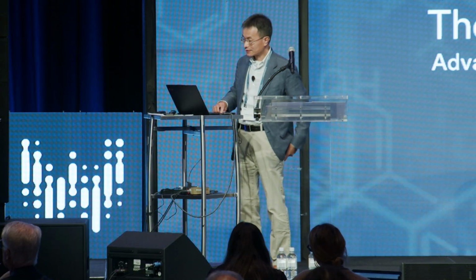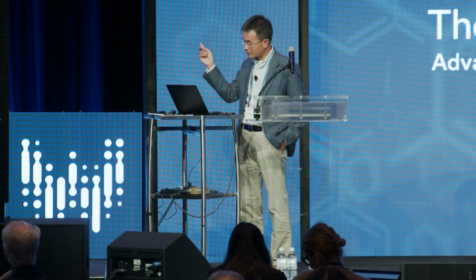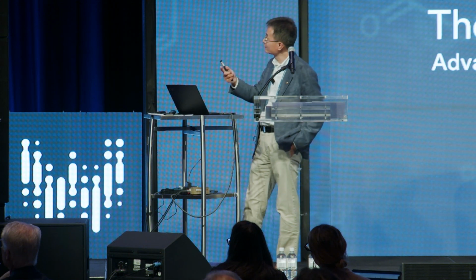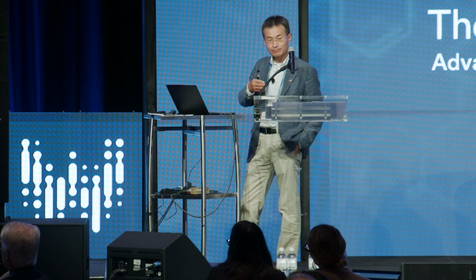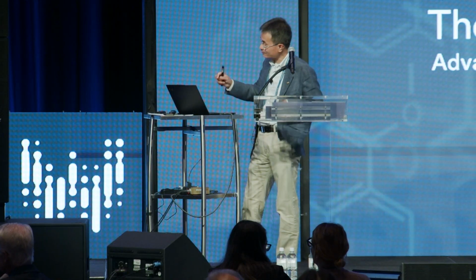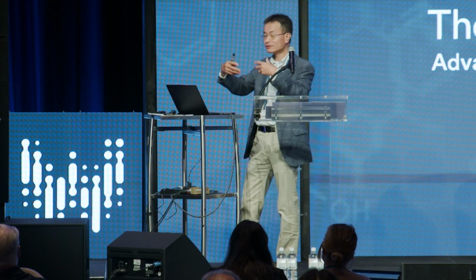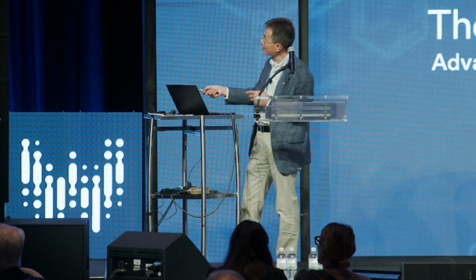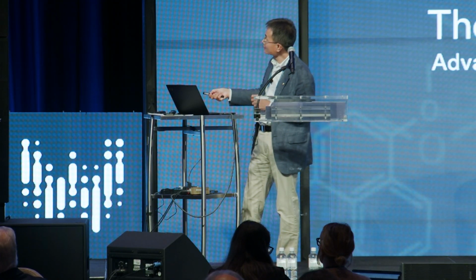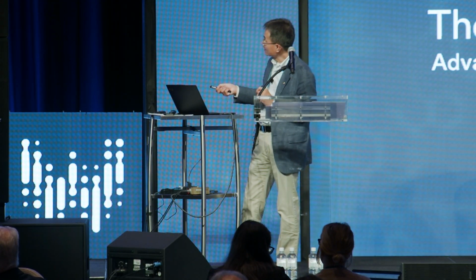So Millie theoretically predicted this back in '93, and after 10 years, I worked with my colleague, Arun Majumdar. Arun has now moved to Stanford. For the first time, we figured out how to quantitatively measure the size-dependent thermal conductivity. This is the platform where we suspended these individual nanowires between local microbeams. You can heat one end, measure the heat through the thermal bridge, then calculate the thermal conductance of this single silicon nanowire bridge. Then you can measure the thermal conductivity as a function of the size, the diameter. You are seeing here from 100 nanometers all the way down to 20 nanometers.